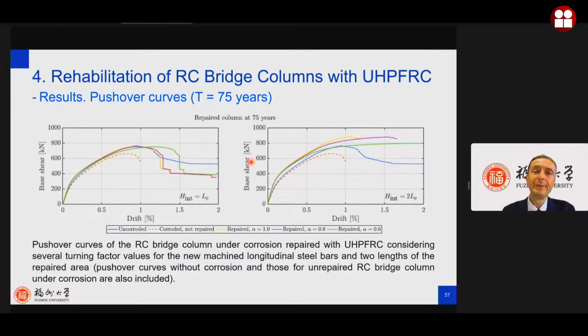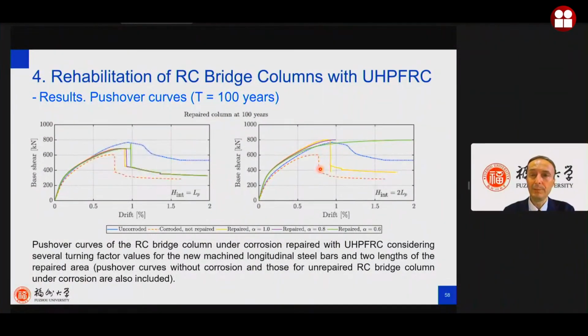But what happens if the repair of the column is considered after 75 years? You can see that if you do it, it changes completely, because you need to have an intervention equal to 2 LP, as you can see here, to still have a good characteristic. So the intervention is influenced by when you do it, and also if you consider the long-time behavior of a bridge. And this is also for 100 years.